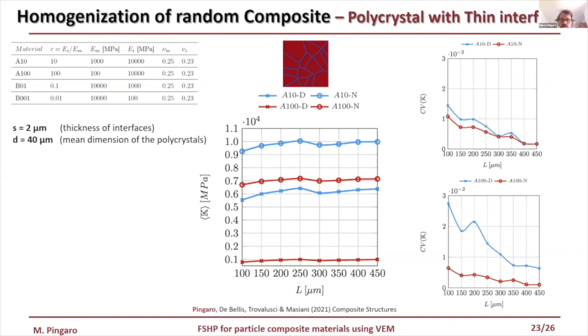As you can see in these two examples, the homogenized bulk modulus remains more or less constant, increasing the window dimension. But the coefficient of variation gives a convergence trend for the representative volume element.